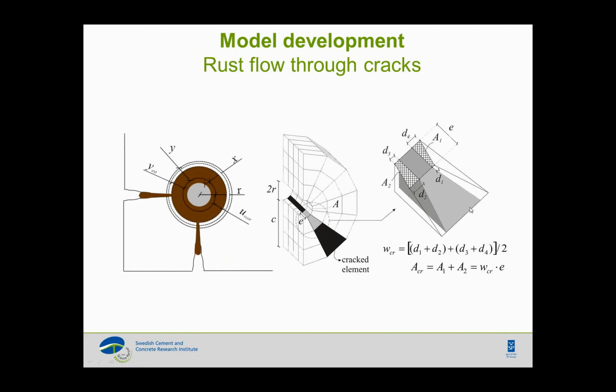We implemented that as a subroutine in our Diana analysis. So we locally get the crack widths from the analysis, and similar to what we do in molecular dynamics analysis, we probe a single molecule of rust moving in the crack. We do exactly the same through a Newtonian formulation. With that, we estimate the volume of rust which manages to flow out through the crack.